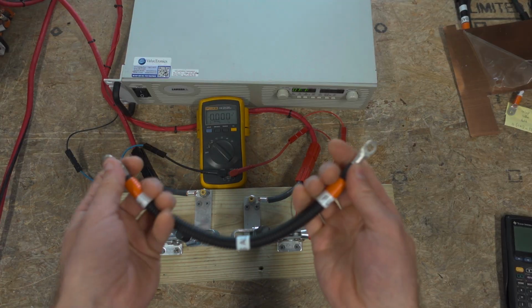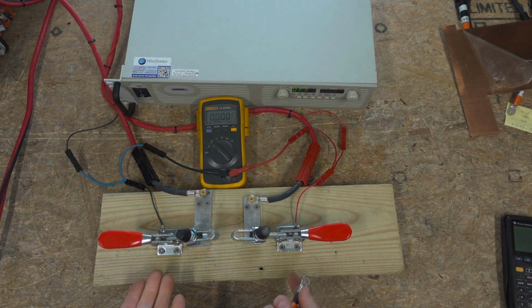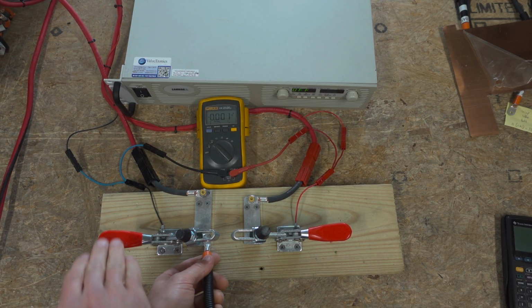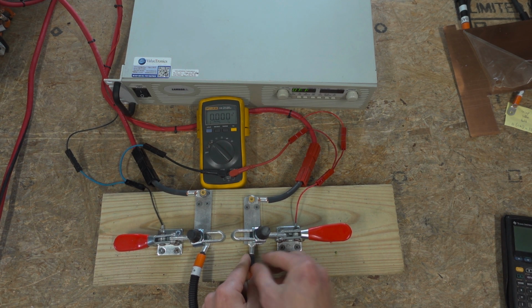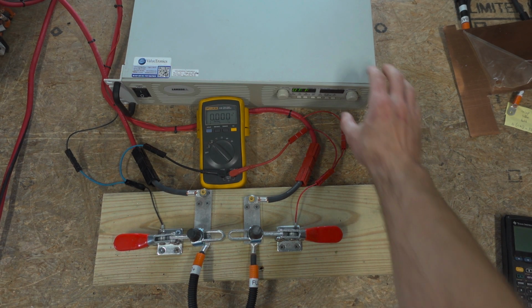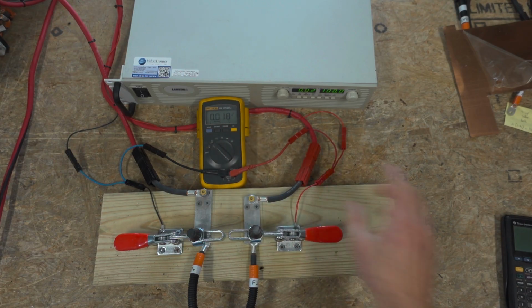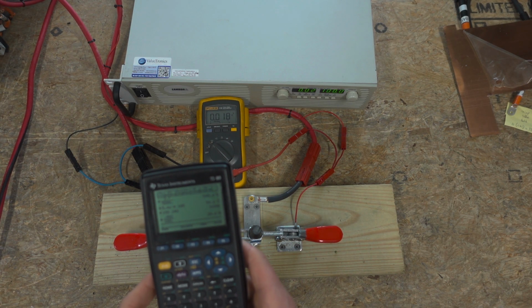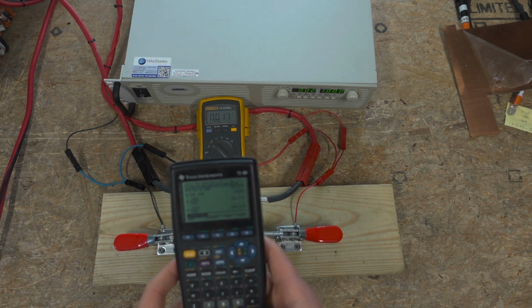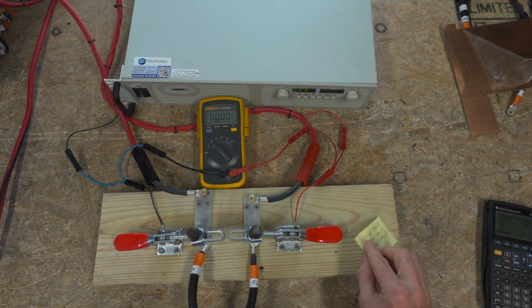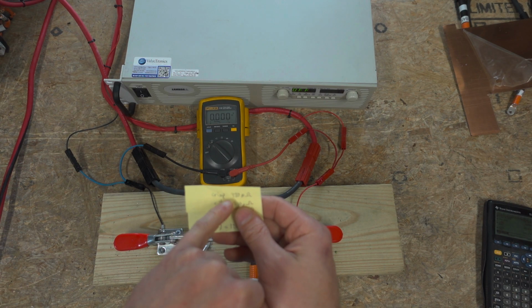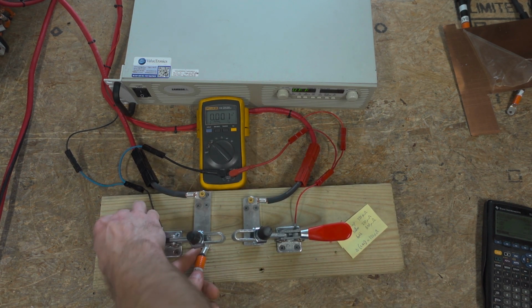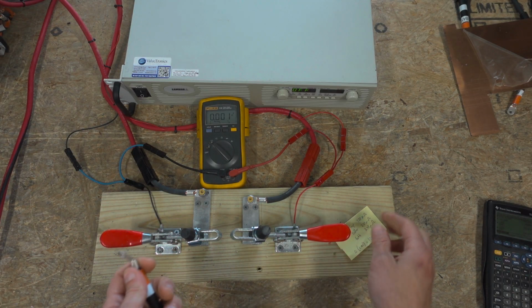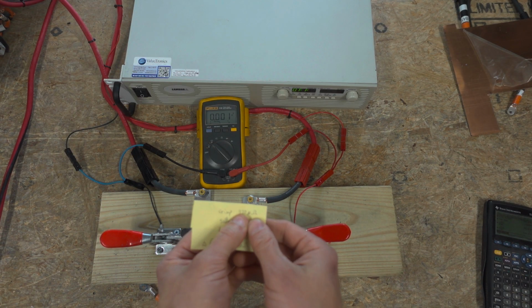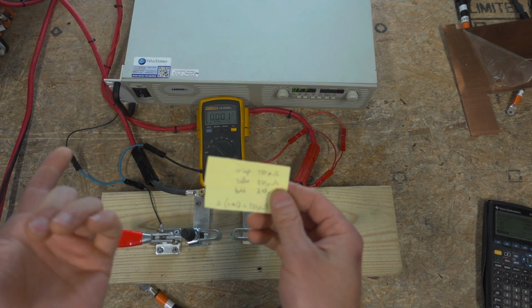So let's look at this cable that I ship, and I test all my cables with it. It's why I have this test fixture. What you do is you take your cable and clamp it down like this, and then you hit go, and you see I have an 18 millivolt drop, so 0.018 divided by 100 amps, you see I have 180 micro ohms. And that's going through 2 connections. In the video I watched, we were doing 1 crimp and a short section of wire. I'm doing 2 crimps and a short section of wire, and I'm getting half the measured resistance. So I'm better than soldered.